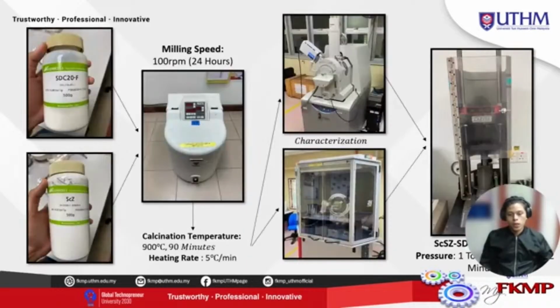Here is the flowchart of creating the electrolyte composite. The first photo shows the SDC and the second photo shows the SCSZ, combined by high energy ball milling at 100 rotations per minute for 24 hours. The ball milling uses zirconia balls and ethanol for combining these two powders, then drying for 12 hours at 100 degrees Celsius, and then calcining the powder at 900 degrees Celsius for 90 minutes. The heating rate is 5 degrees Celsius per minute.